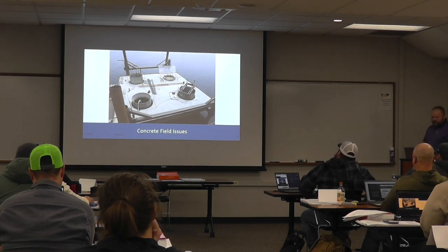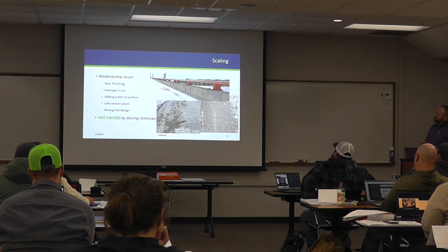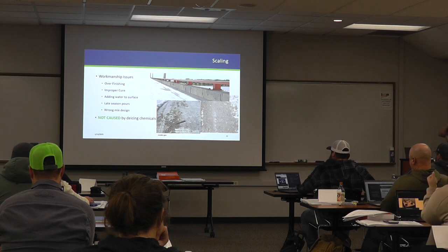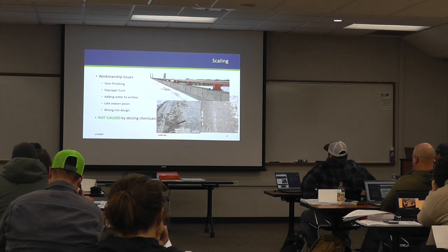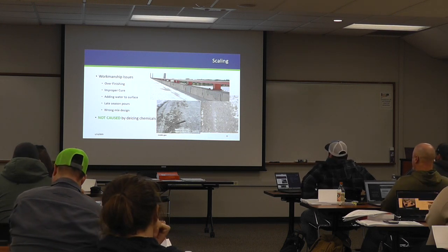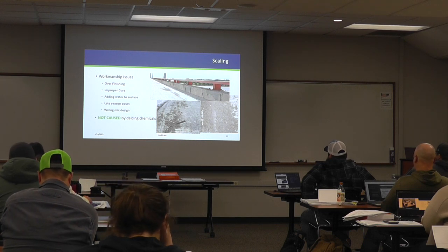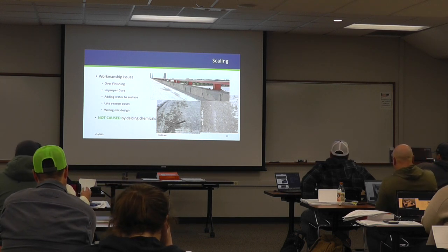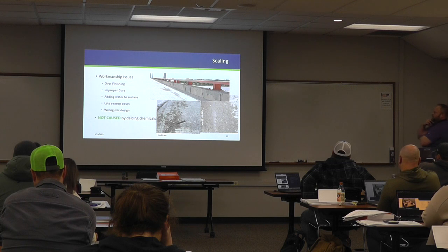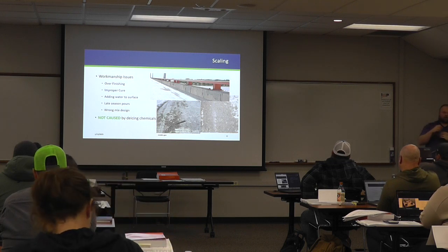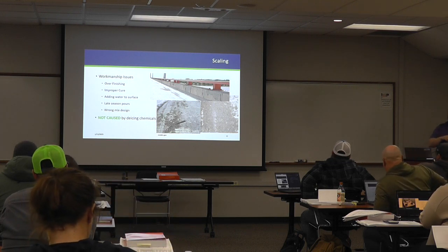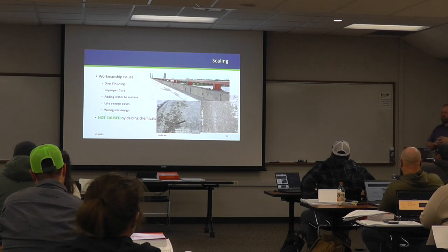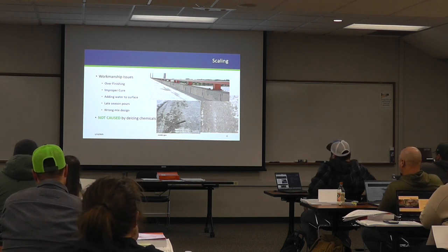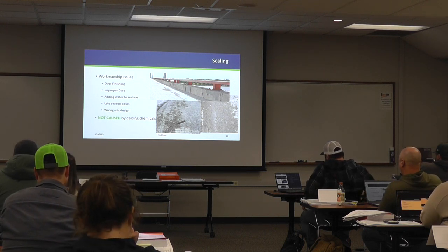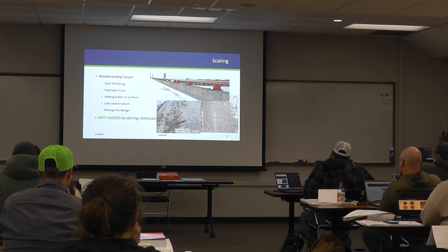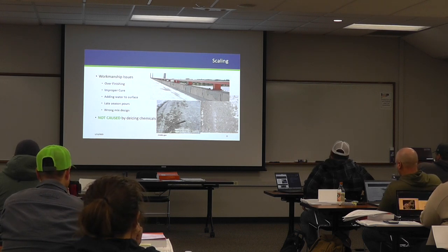There's only one. All right, let's talk about concrete field issues. So scaling, this is a big one. We always hear, well, it's the salts that cause scaling. More often than not, when we see scaling out on MnDOT projects, we take a core and put it under the microscope. It's either over-finishing, like improper finishing, or curing that has caused the scaling to occur. Now, de-icing chemicals are not the root cause of scaling, but they exacerbate it.